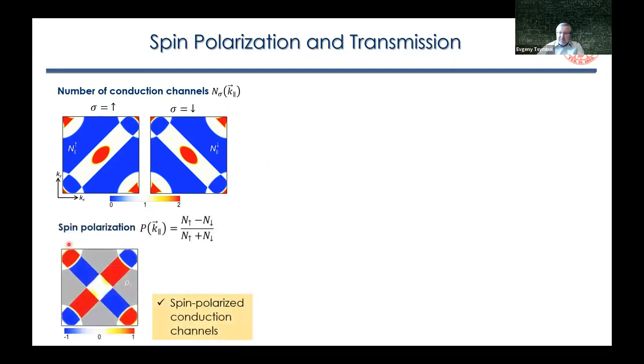As you can see, the shapes are also congruent, as with the Fermi surfaces, but again, they're not the same. Specifically, this difference can be seen from the fact that we should have spin polarization of each conduction channel. If you fix k parallel, the transverse momentum, in this two-dimensional Brillouin zone and calculate the difference between the numbers of conduction channels normalized by their sum, you can see that we have a spin polarization which is distributed in this two-dimensional Brillouin zone. We have plus one, minus one, or zero, depending on what part of the Brillouin zone we are in.